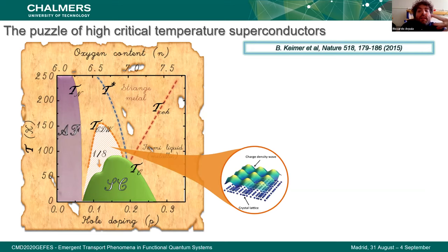The interest is given by the visible competition between the charge order and the superconductivity, which is highlighted by the fact that charge density wave is maximum at the 1/8 doping level, which corresponds to this depression of the superconducting dome. However, the ability of charge density wave to influence the properties of the cuprates, both in the superconducting and in the normal state, has always been questioned. This is mostly because charge density wave, as you can see here, only occupies a very small region of the phase diagram, only in the underdoped part, and only below the pseudogap temperature.